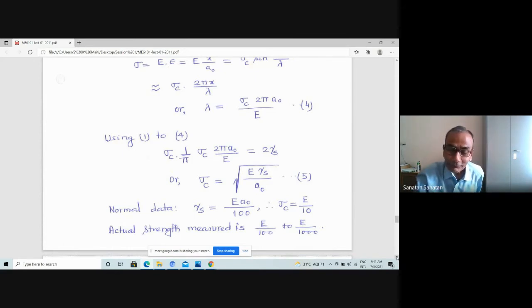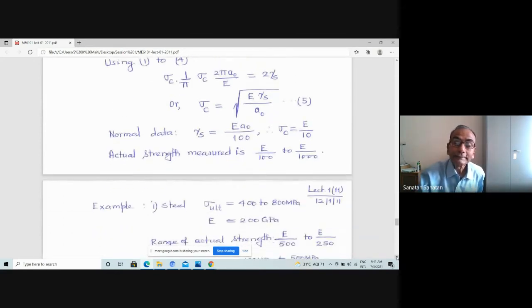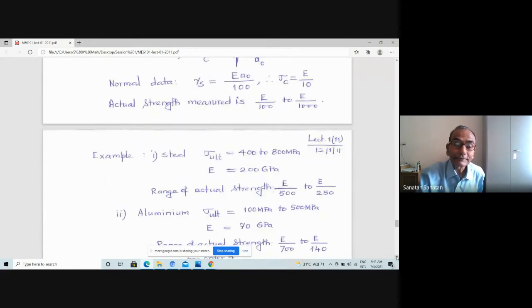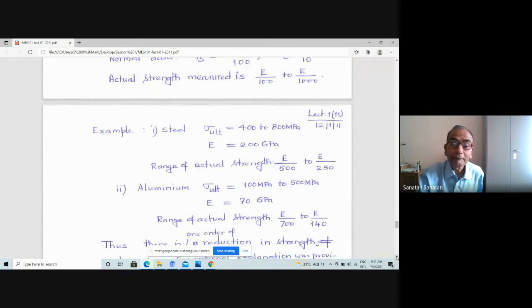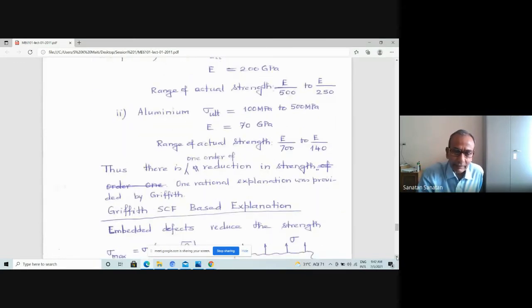This model, which was initially given, really got entangled in these questions. If you consider a few materials, let's say steel, the ultimate limit is about 400 to 800 MPa and E is 200 GPa, then the range of actual strength is E by 500 to E by 250. That is much less than the theoretical strength. For aluminium, the ultimate stress is about 100 to 500 MPa and E is 70 GPa, and the actual strength range is E by 700 to E by 140. Theoretical strength is E by 10, but these are actually E by 100 and more. So the question is, what happens? The theoretical strength does not correspond to the actual measurement that we see. That became a concern: why is the actual strength much less?